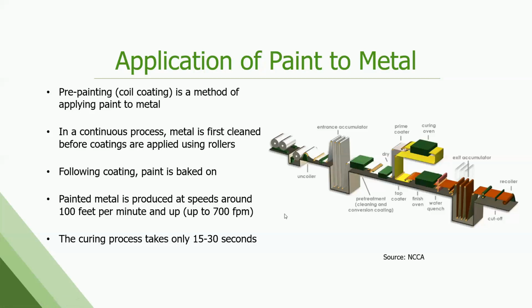So this is a kind of a typical generic coil line or paint line. They tend to be very, very long. Our lines, for instance, can hold up to 2,500 linear feet of metal from end to end, so they're big, typically 3 to 8 stories tall. We load the metal coil at one end. It's a continuous process, runs through the line, it gets cleaned, gets some pre-treatment, gets a primer, gets a top coat. Those are baked on at very high temperatures.